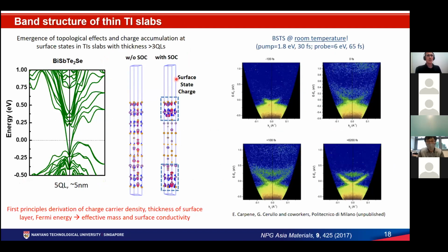The material platform that we use, this BSTS, is bismuth, antimony, tellurium, selenide. By doing first principle DFT calculations, we observed that when you calculate it in a slab, you observe the bulk band inversion and the appearance of the Dirac dispersion bands at the gamma point. One other interesting thing the DFT calculations show is that when you turn on the spin orbit coupling, you see the surface charge state start accumulating, which is a clear sign that you have surface states building.